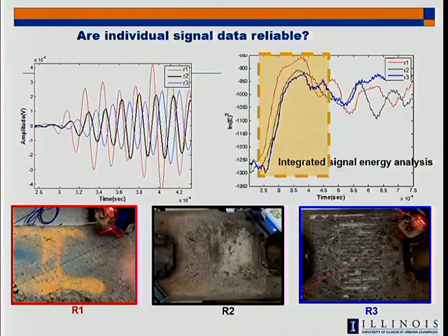Okay, so remember that moving integrate. Now we found that velocity doesn't change very much, so it's not a very sensitive tool, but can we use the energy? Again, we're using this moving window and getting this kind of envelope of the energy, which you can see from these curves. They look like diffusion curves, which people use to model that and put a number to. I just put the pictures here. There are three different levels of RSD. R3 is the worst, R1 is the best, meaning least.